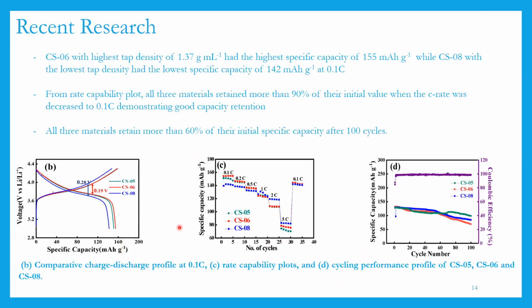And so some of the electrochemical analysis that we did. So this first plot is basically comparing the charge-discharge capacity of the 3 samples that we selected. We found the material with the highest tap density, which is CS06, had the highest specific capacity, about 155 milliampere hours per gram. And then the material with the lowest tap density, CS08, had the lowest specific capacity. So C rate is basically how fast you charge these samples. So if you use a 0.1 C rate, you basically take 10 hours to charge and 10 hours to discharge. Whereas if you use, let's say, a 1 C rate, then you basically take 1 hour to charge and 1 hour to discharge.